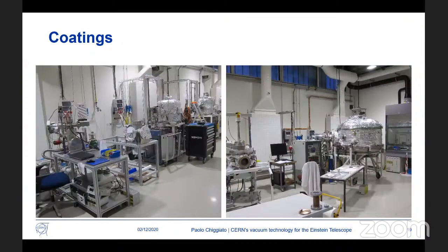In addition to long vacuum chambers, we coat also samples of different materials. For example, we can coat mirrors, glass, polymers, and ceramics. We can coat with a very, very thin layer of titanium ceramics to avoid charge build-up on the surface of this material.